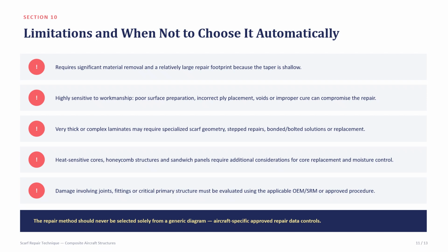It requires significant material removal and a relatively large repair footprint because the taper is shallow, and it is highly sensitive to workmanship. Poor surface preparation, incorrect ply placement, voids, or improper cure can compromise the repair. We have to verify that a thick or complex laminate may require specialized scarf geometry, stepped repairs, bolted or bonded solutions, or replacement. And heat-sensitive cores like honeycomb structures and sandwich panels require additional consideration for core replacement and moisture control. Damage involving joints, fittings, and critical primary structures must be evaluated using the applicable SRM or approved procedures. This repair method should never be selected solely from a generic diagram. It should have specified, approved repair data control.